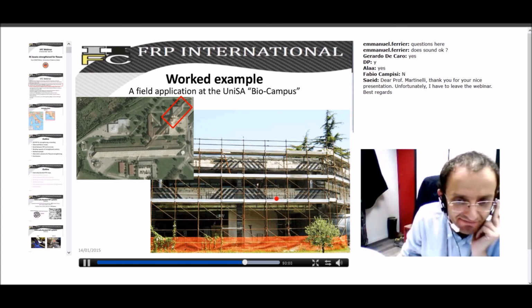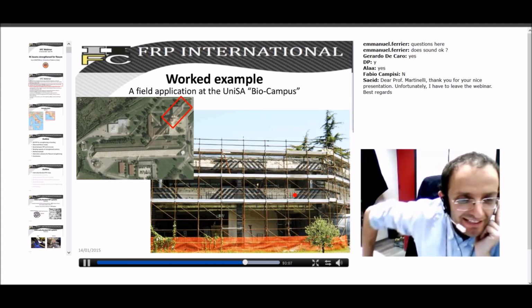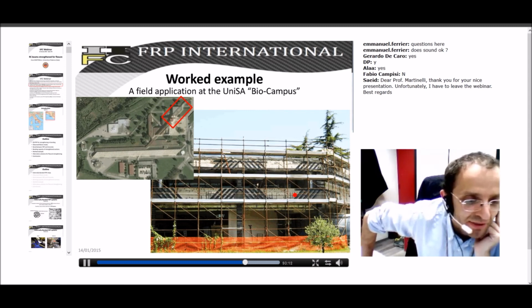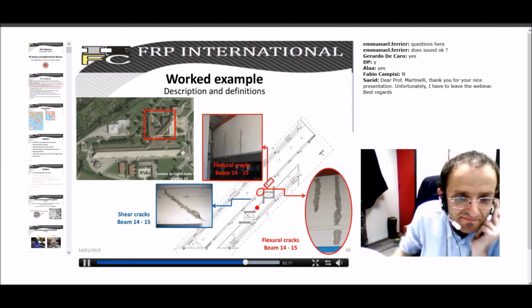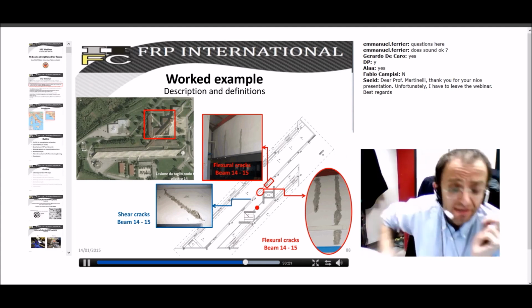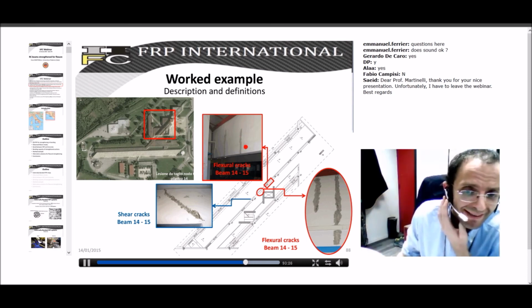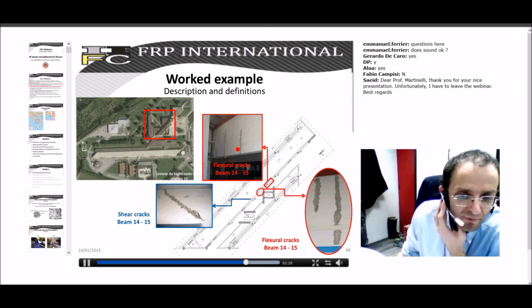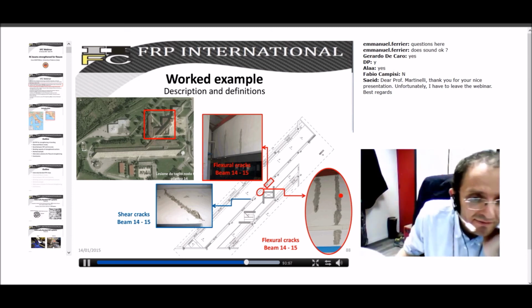In shear, you see these inclined FRP strips, linked to shear strengthening, which will be covered in the next presentation. But here they did also some flexural reinforcement, because they found also some bending induced cracking. These are orthogonal cracks, so these are clearly bending induced cracks. We have very long beams spanning around 10 meters, which are probably under-designed, because these were designed in the 70s, and now maybe they experience some increase in loads, and they are probably under-designed for the current needs. So they exhibited some cracks, and since the designers were concerned about these cracks,